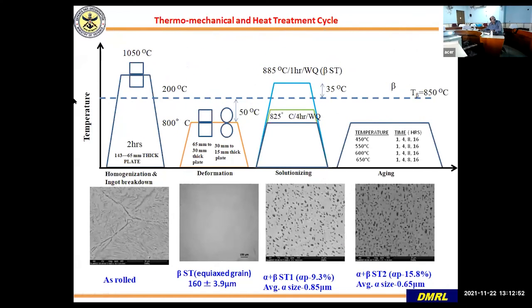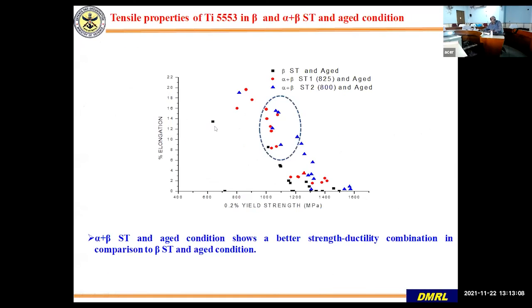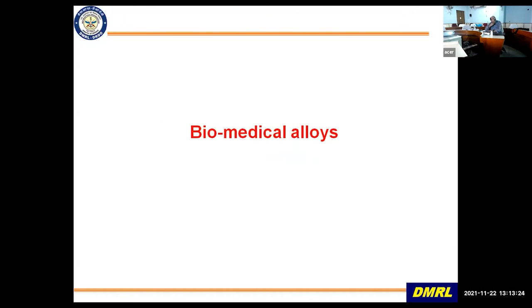And this is how it was processed: ingot in beta regime, then alpha beta process, then solutionizing at different temperatures and aging at different temperatures. These are the different microstructures which we generated, and we generated a lot of mechanical property data, and alpha plus beta treated material showed good combination of strength versus elongation. So we are now going in for industrial scale melting and processing for program of ADA.